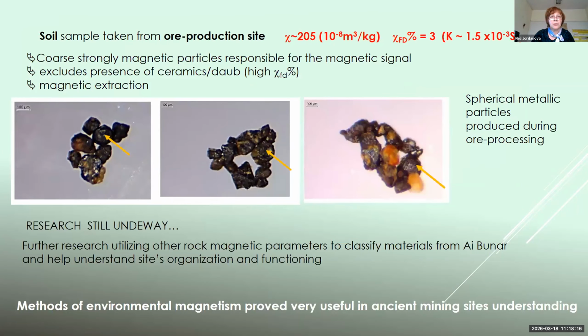From the soil sample, which was taken from the ore production site, which showed very high magnetic susceptibility but low frequency dependence, we did a magnetic extraction, and as a first result, we got the presence of metallic particles of spherical shape, which are probably produced during ore processing with the use of fire.